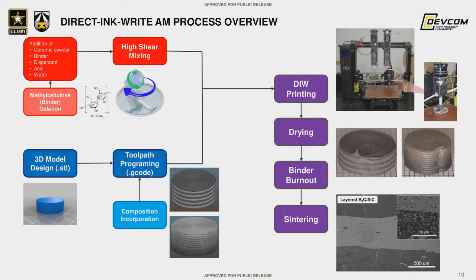So taking all those together, we can give you an overview of the AM process for direct ink write. It really starts with the ceramic powder, which is a mixture of ceramic powder, polymer binder, dispersant, acid, and water that we put through a high shear mixing process to create these smooth and well-mixed inks, roughly with a shear thinning behavior similar to peanut butter.